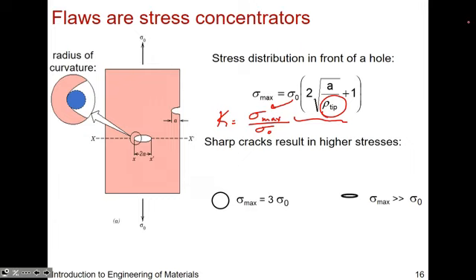If your crack is more ovalish, right, it's a smaller crack, but you have a smaller radius of curvature, but it's longer, right? That can concentrate the stress more. And you can do this analytically by going to just Wolfram Alpha and showing it. And you could see the applied stress versus what you experience for a crack.